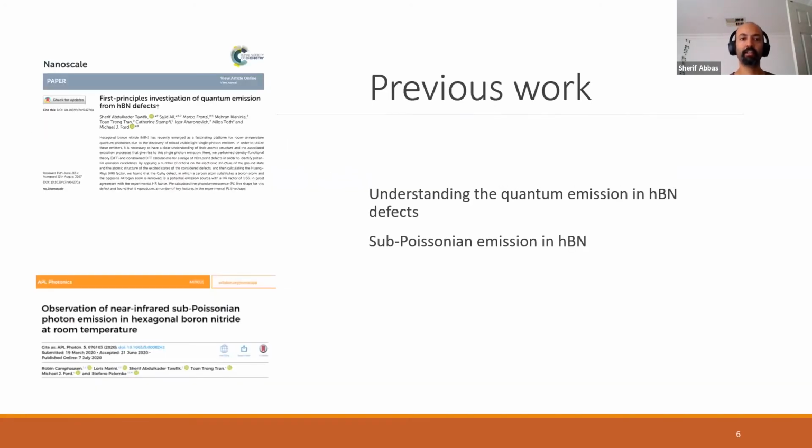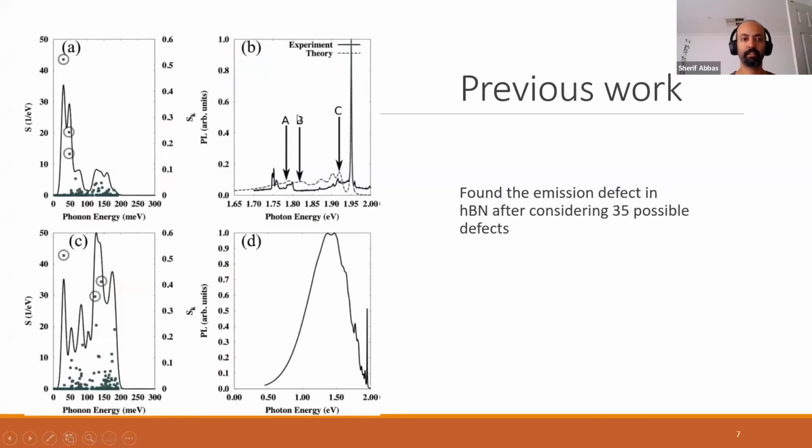And in particular, in that first paper, the Nanoscale paper, this was the key output. So I had photoluminescence properties of hexagonal boron nitride defects at 4 Kelvin, and that's the black line here. And then using VASP plus code that I developed, that's the calculated line shape, which is not overlapping with the experimental line shape, but at least it qualitatively agrees with it.